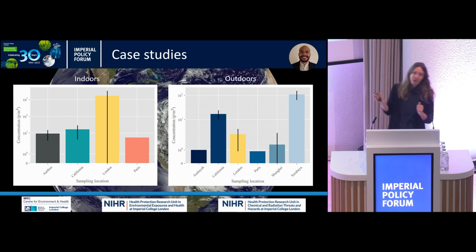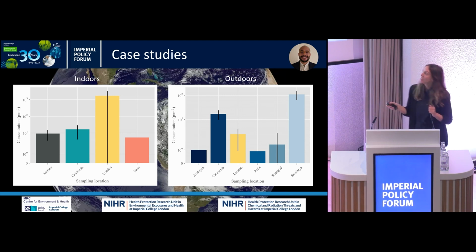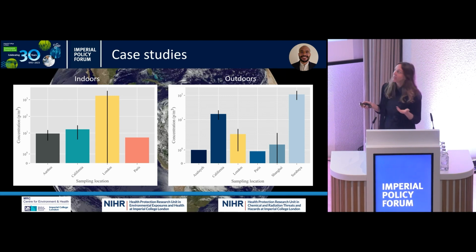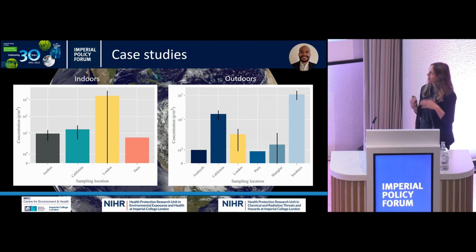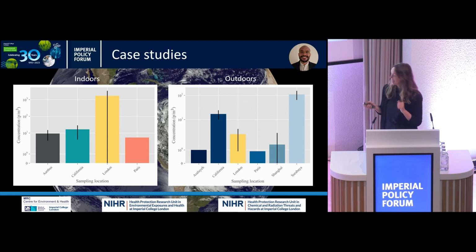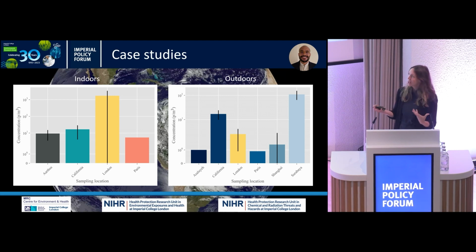And the reason why we hypothesized that is because you can see this big error bar here in respect to our number concentration. So we found around 1,700 microplastics per cubic metre on average. We sampled over a 4-week period, and each week we saw a drop-off in the numbers. And funnily enough, we were approaching Christmas. So we just think that students were going home for Christmas in that time, and there was no one actually using the gym anymore. So that's why we hypothesized it was probably coming from the local population density in that environment.